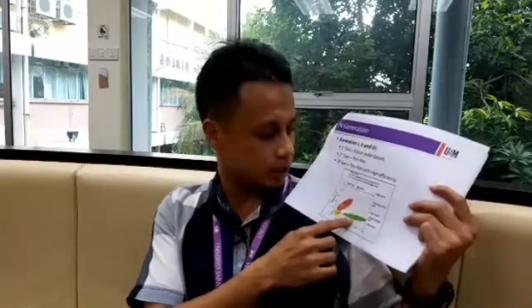So about there you can see the grains clearly. So the efficiency is about 16 to 25 roughly. If you use multicrystalline, those with grains, the efficiency ranges from 16 to 20%. Whereas if you use single crystal, the efficiency is about 20 to 24, 25. Currently the world record is being held by University of New South Wales. So the lab scale efficiency is about 25 point something percent back in 1998.